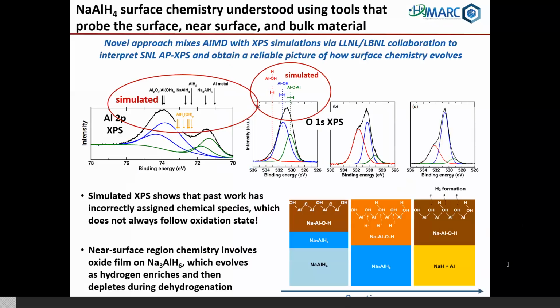And the prejudice, I think, or preconceived notion up till now has been that oxides are bad. They contaminate the surface. If they're too thick, of course, they can block the access of hydrogen to the rest of the material. These experiments and calculations suggest that under controlled conditions, one may actually want an oxide layer, a very thin oxide layer, and we're looking at that now in other metal hydride materials to see just how general that phenomenon is. Next slide.